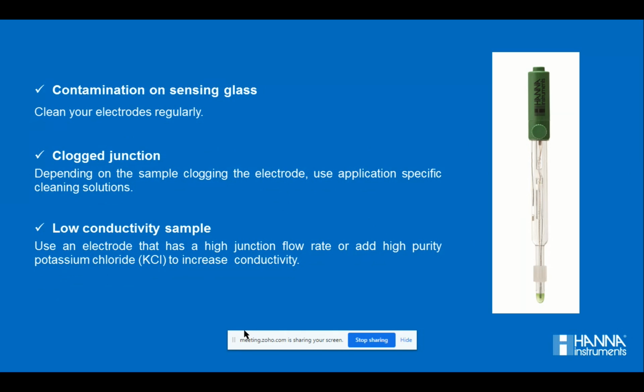Then another unidentified problem is a clogged junction. Many people do not understand whether the junction is clogged or not, mainly when they are using a ceramic junction or a cloth junction electrode. Ceramic junction is very susceptible to getting clogged when you have high contamination and high conductivity in your sample. Other junctions like a sleeve junction, open junction, or even Teflon junction have very low susceptibility to getting clogged. But if your junction gets clogged, you might see a very slow response and drift in the reading, because as the reference junction is clogged, the reference electrode doesn't come in contact with the sample, thus the electrode will not have stability in pH measurement.